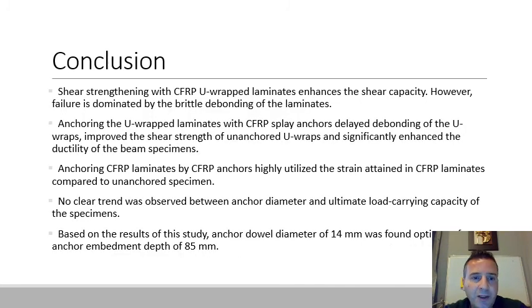So in conclusion, shear strengthening with CFRP U-wrapped laminates enhances the shear capacity. However, failure is dominated by the brittle debonding of the laminates. Anchoring the U-wrapped laminates with CFRP splay anchors delays debonding of the U-wraps, improves the shear capacity of the unanchored U-wraps, and significantly enhances the ductility of the beam specimen. Based on the results of this study, the anchor diameter of 14 millimeter of splay anchors was optimum with an embedment depth of 85 millimeter.